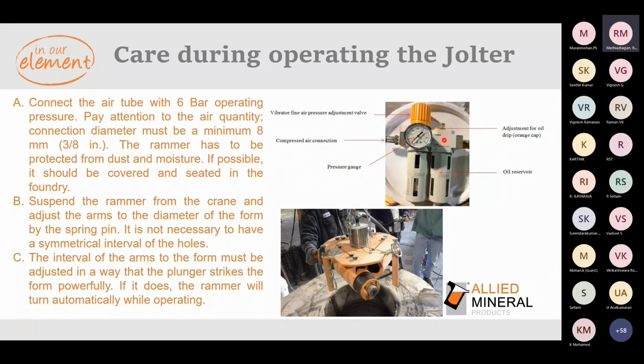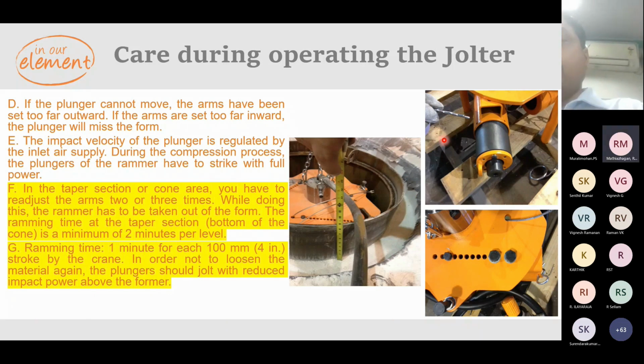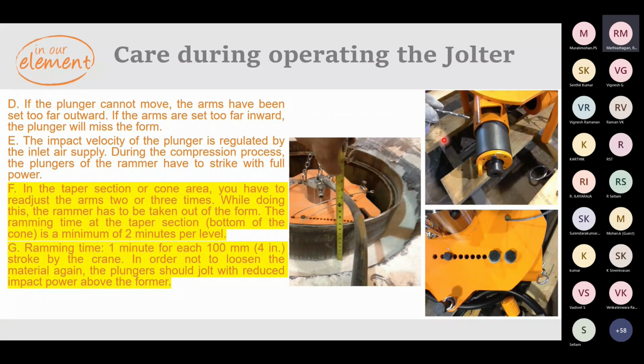Care has to be taken while using this vibrating system: it should be operated at 6 bar pressure. Pay attention to the air quantity, so use a minimum of 8 mm hose for the airflow between the compressed air and the system. The rammer should be dust free, because it has a lot of moving parts. Adjust the arms according to the form diameter. Make sure the vibration is happening properly with a vibro tachymeter. Use a vibro tachymeter to understand the vibration and note it down, so that every time you cross check it, if any deviation is there in the amount of vibration being transferred, you can check your pneumatic vibrator or Jolter.